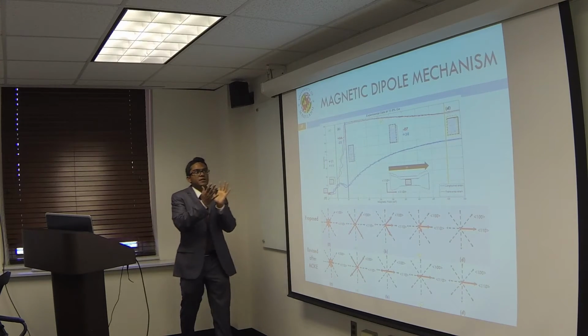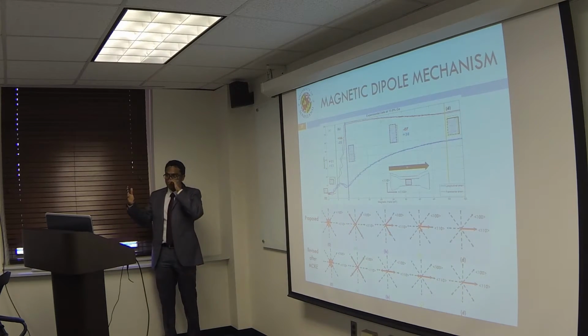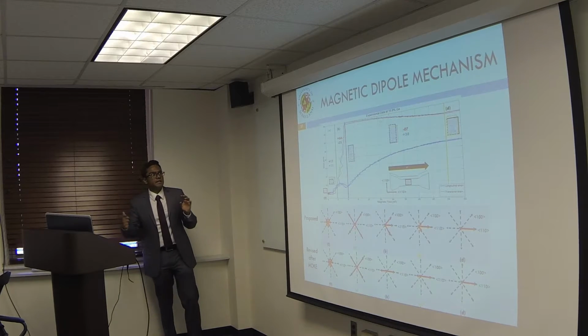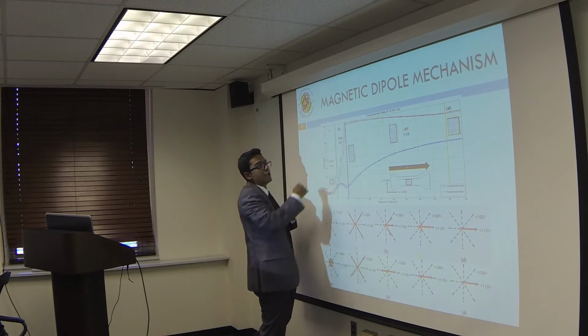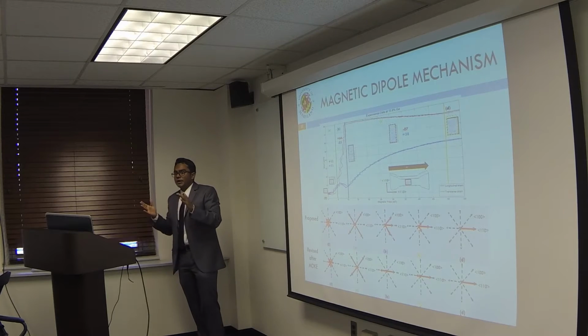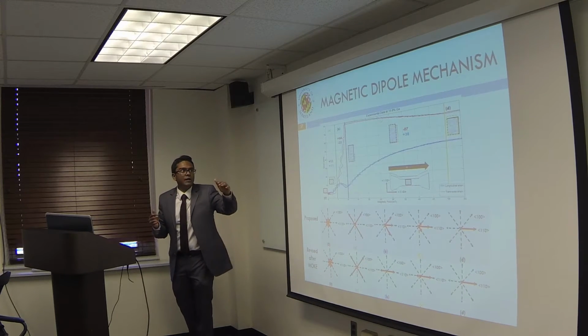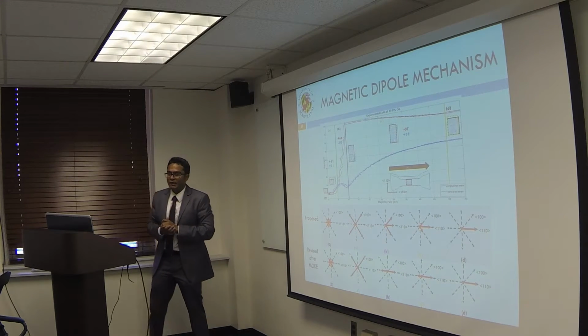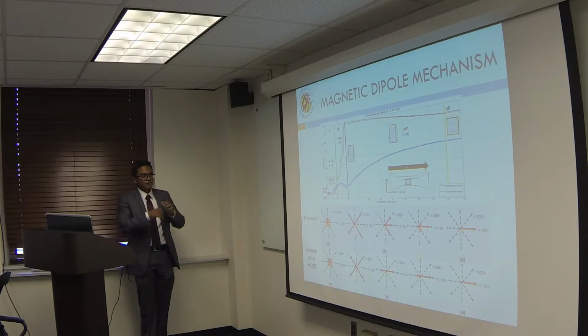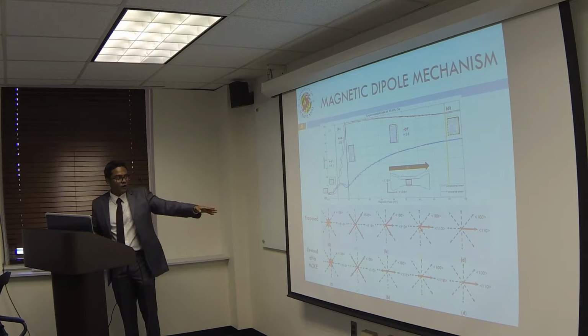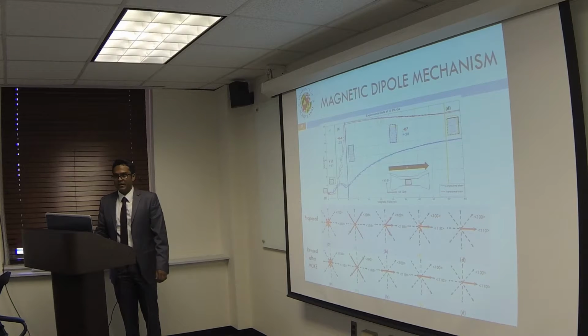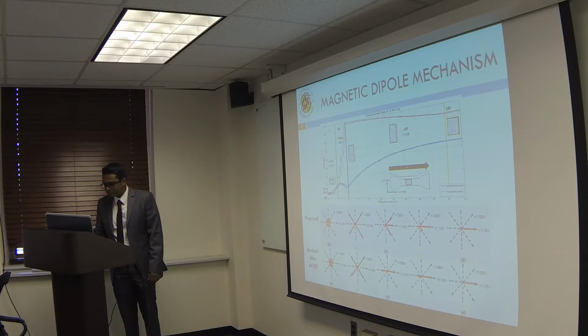So magnetostriction in Galfenol occurs as a burst along the 110 direction, and since it's already achieved a large value of transverse strain, we continue to be auxetic even though there's a shrink along the transverse direction. So this was very exciting for us, and we modified the dipole mechanism that we proposed earlier.